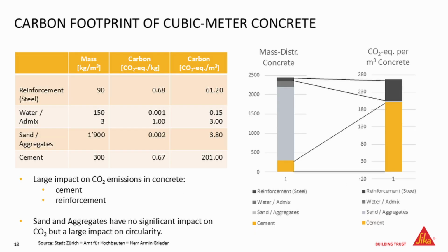So then the city of Zurich looked at the concrete, and they looked at the mass distribution of the concrete. I think we are all aware of that. And they looked at the carbon footprint of the ingredients. And basically what you see, and I think we are all aware of that, is that from the mass, it's the aggregates, that is clear. But from the CO2 equivalent, that's two parts. That is the cement, and this is the reinforcement. So from a circularity aspect, the aggregates play the biggest role. From the CO2 perspective, cement and reinforcement.